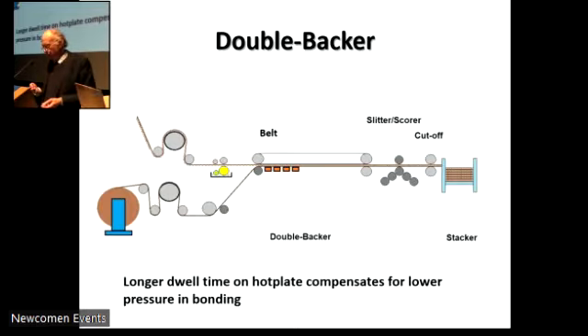Again, we have application of the starch to the surface of the flute tips on the single-face board, combination with usually the outer liner, and contact with the hot plate to cure the glue. The important difference between the double backer and the single facer, well, there are two. One is we're not making flutes, they're made already. The second is because the flutes are there, we can't apply a lot of pressure to get the glue to set. More pressure means more granule rupture and better heat transfer.